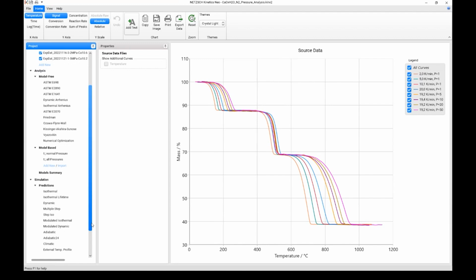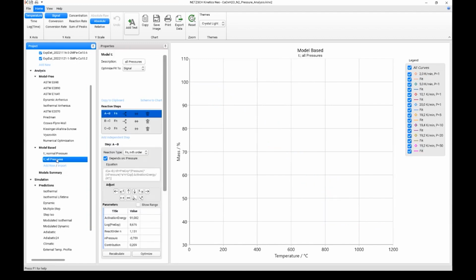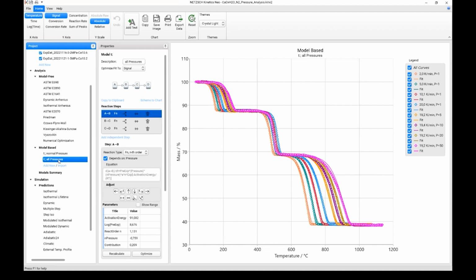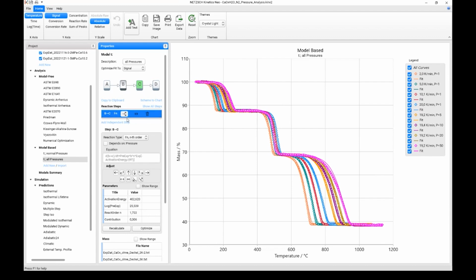And then we have the already created model-based reaction kinetics, which has 3 steps. A goes to B, B goes to C, C goes to D. And for each step, we can select whether a dependence on the pressure exists or not. For example, for the first step, A goes to B, the dependence on the pressure is switched on. For the second step, B goes to C, the dependence on the pressure is switched off. It is not present. Here we have only dependence on heating rate, dependence on temperature as usual.